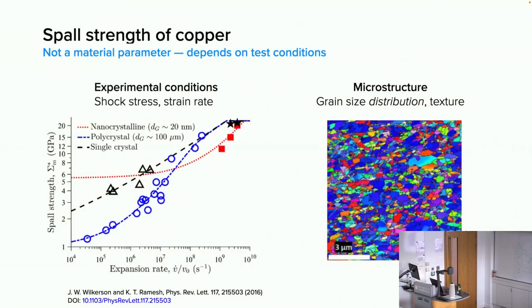Okay, let me give you just one example of some of the data that we can collect and the kind of experiments that we can do. So this is from a paper by Justin Wilkerson from a few years ago where they were looking at the spall strength of copper in different forms, single crystal, polycrystal, and nanocrystalline. Spall strength is a function of the expansion rate. This is the expansion rate of the voids. You can think of it as being related to the strain rate. The data that are here, these experimental data points, are a significant fraction of all the experimental data that existed for polycrystalline copper at the time that this paper was written.